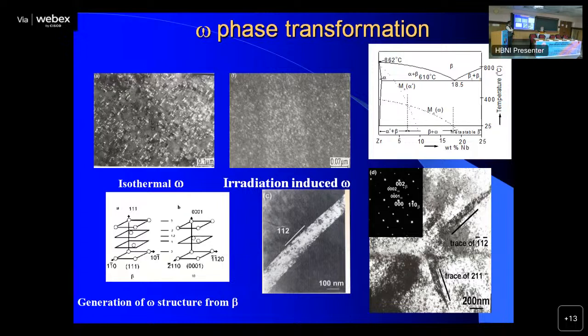is the one that shows various types of martensite in zirconium-based alloys. Zirconium shows the largest range of martensites, much larger than what steels can show. And all that has been mastered to the hilt by the scientists from BARC. Here I talk of another phase, which is not a desirable phase, which is the omega phase.